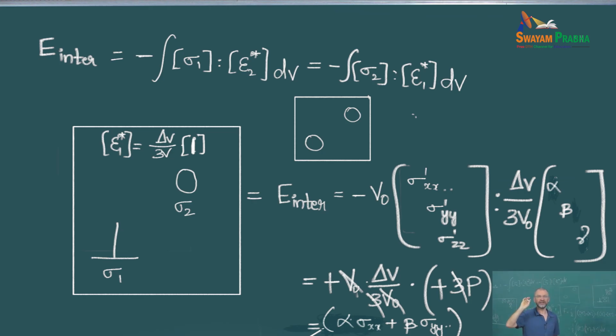For those who have already seen that, I don't know if anyone of you knows. Actually, it's a bit surprising that the stress field outside of the Eshelby inclusion is only shear. There's no pressure produced by the solute outside of itself. It only creates shear and no pressure.